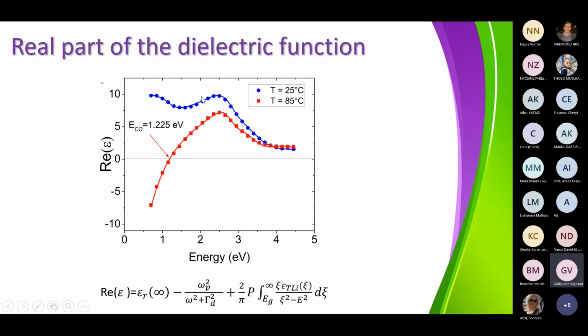And you see definitely that if you look at the real part of the dielectric function, it's very different. You go negative in the real part of the dielectric function. Why that? Because you see here that the Drude is negative. This is positive, but there is a minus sign in front. And the Drude is going to give you some negative component to which you will add this quantity and this one, and in the end, you will get something like this.